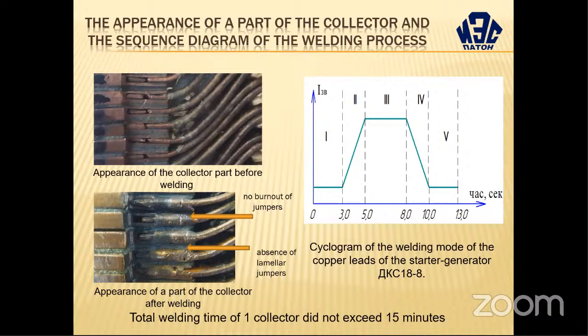The main condition for high-quality welding of base bars with collector plates is the absence of lamellar jumpers, which is possible when melting metal. In this case, due to the optimal modes, they are absent. Similarly, due to the high thermal conductivity of copper, the short duration of the welding process and low welding current, there was no burnout of the lamellar plates. As a result of the experimental work, a cyclogram of the welding process was constructed, which includes gas purge time, current rise time, welding time, current drop time, and gas purge time after the completion of the welding process in automatic mode.